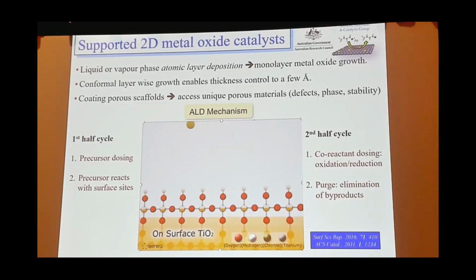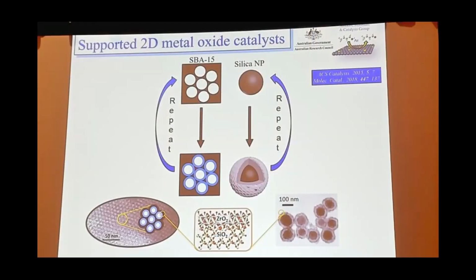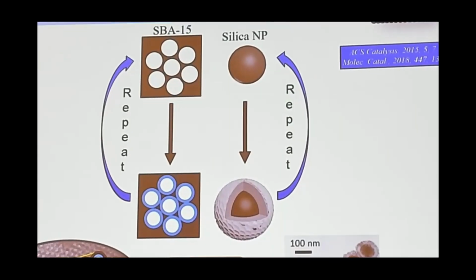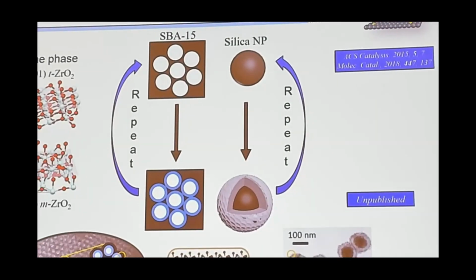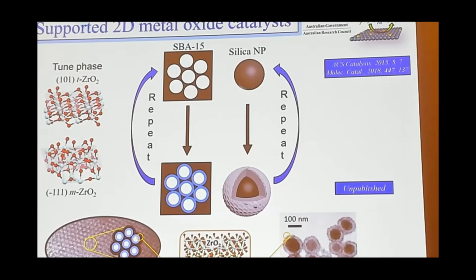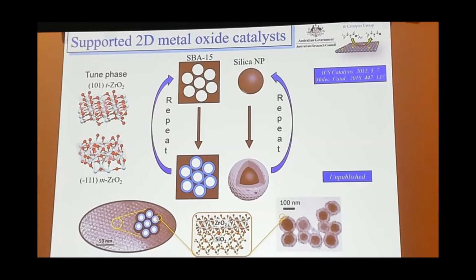So the idea is you can get layer by layer growth in a conformal way over porous scaffolds. We can do that with liquid phase precursors or from the vapor phase. So what we've been doing, for example, is taking SBA-15, coating it with zirconia, and taking silica nanoparticles, coating them with zirconia. The reason that we picked zirconia is because it's a very hydrothermally stable material, so it's ideally suited to the transformation of biomass molecules in aqueous medium.